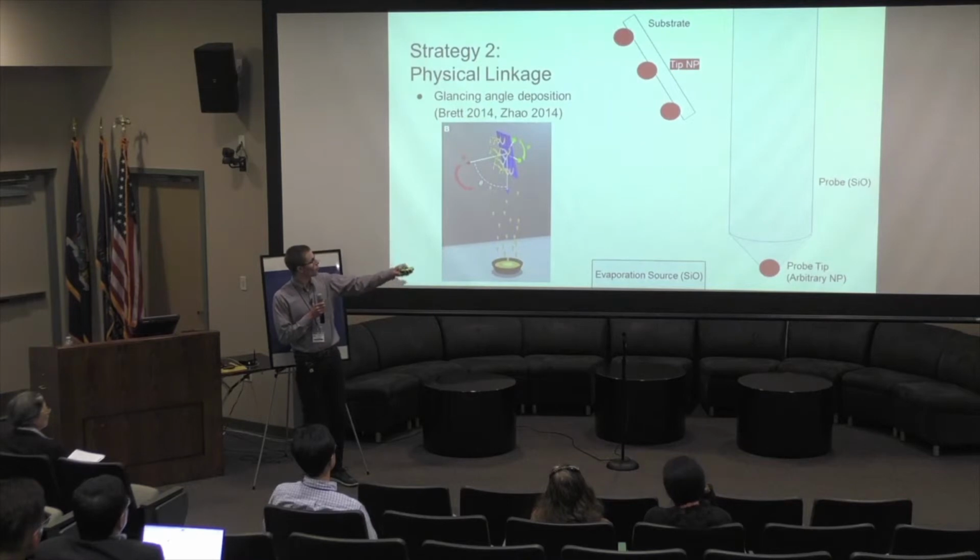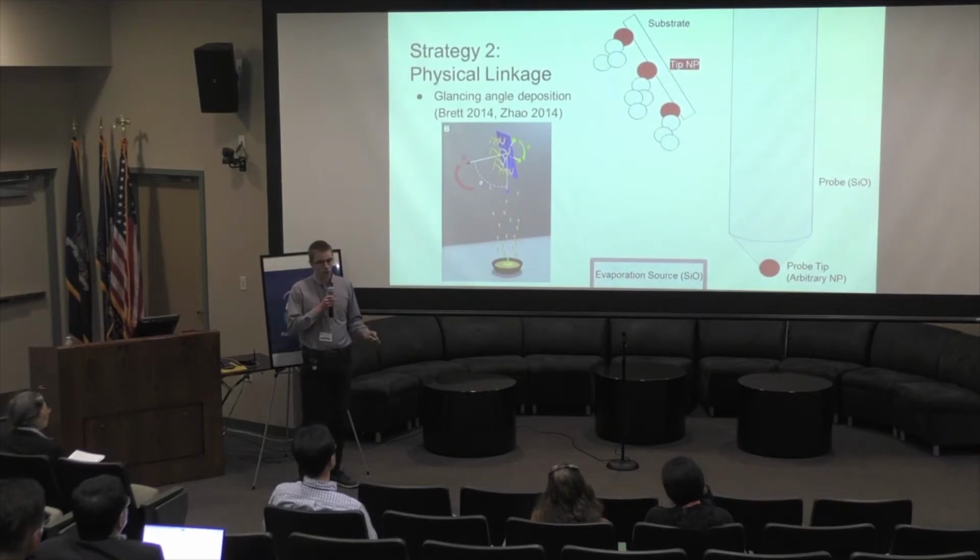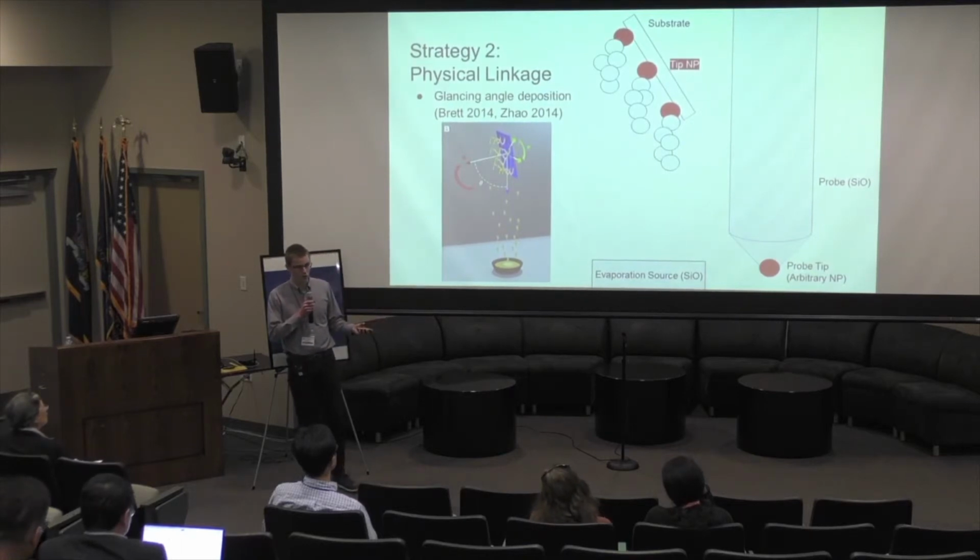You get a small particle. It'll go on a substrate. You tilt the substrate, and then atoms will impact it and preferentially grow into rods off of the small particles. Our hypothesis is then we can detach these nanowires, which are now silicon nanowires with a magnetic nanoparticle on the tip. And this can function just as well as the spatial probe that we were thinking about earlier.